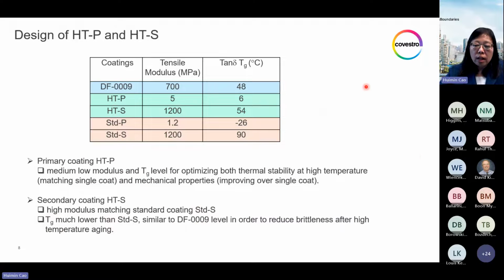With that understanding, we designed our new dual-layer system with non-urethane acrylate chemistry to avoid those failure modes. The HTP is designed at a modulus level of around 5 megapascal, slightly higher than a regular primary coating, to avoid the severe network breakdown from transition, but still significantly lower than the single coat DF-0009.